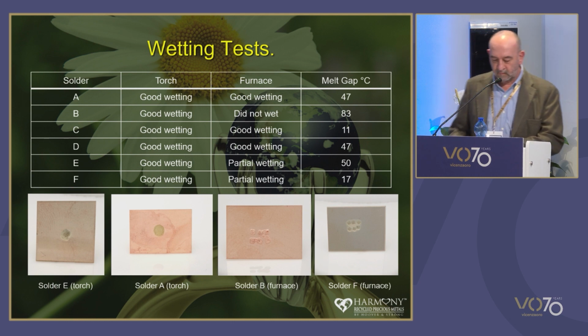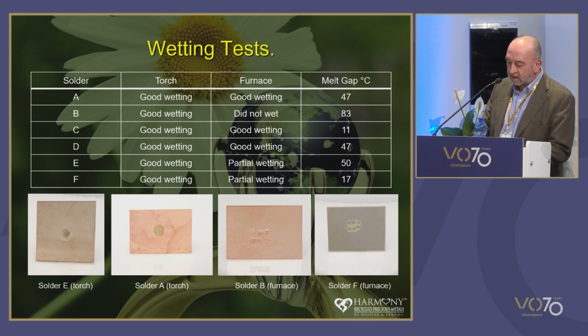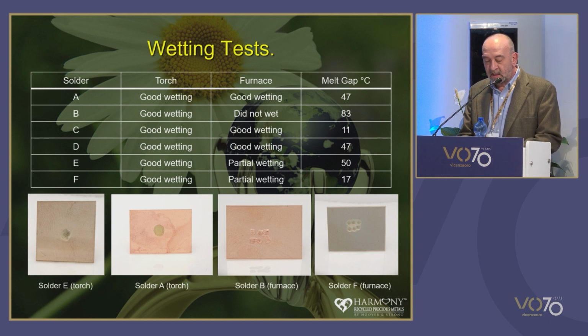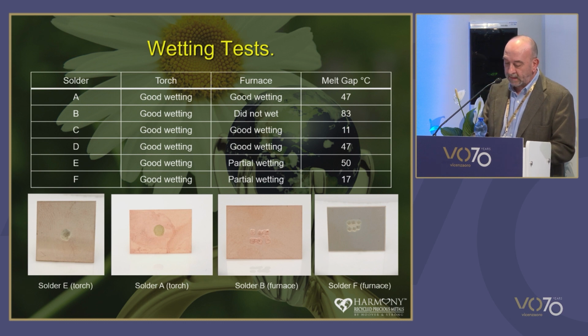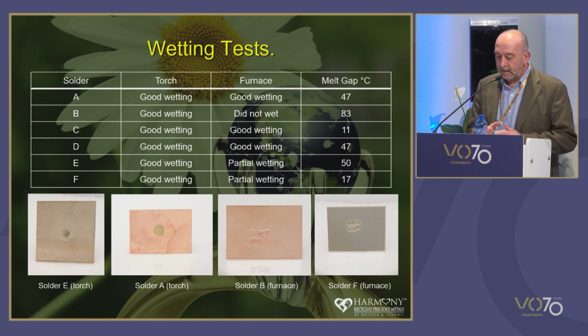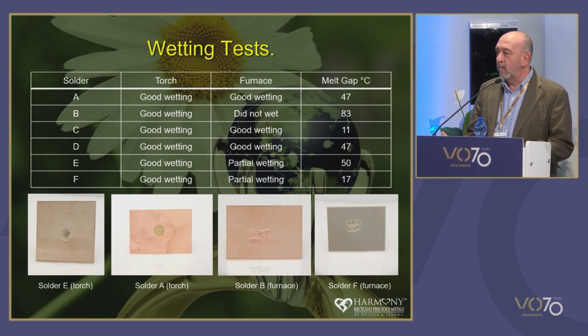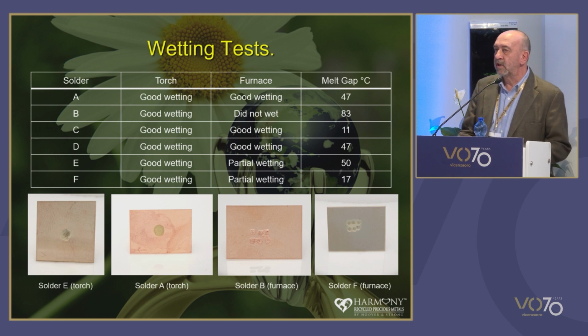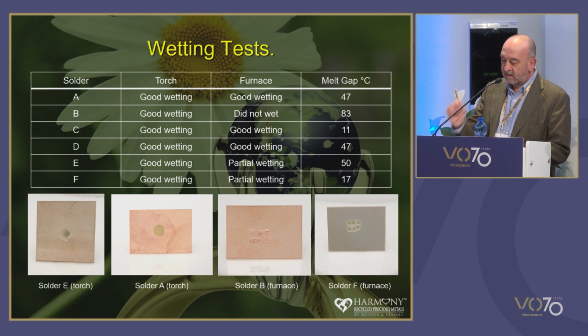It looks horrible. Solders E and F, that are the white gold solders, showed signs of some wetting in the furnace tests, but again, we could see some of the residual solder pieces in there. So the furnace results may be exhibiting a phenomenon where diffusion of the lower melting point constituents in the parent metal raises the flow temperature of the solder remaining in the piece to a melt point above the set temperature of the furnace. So the remaining solder doesn't melt.